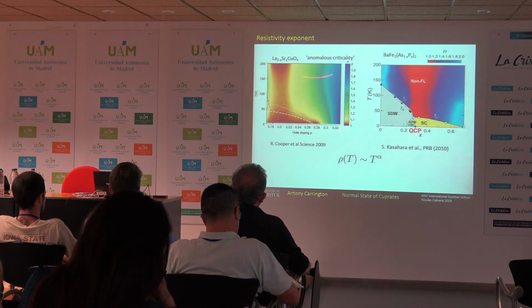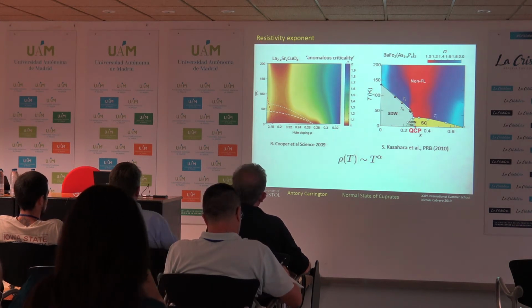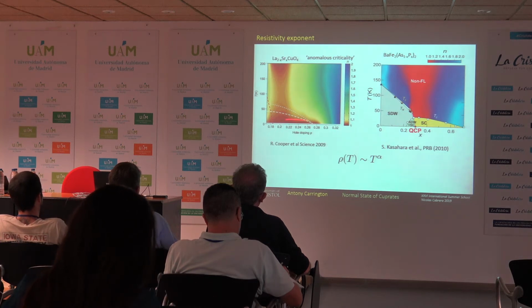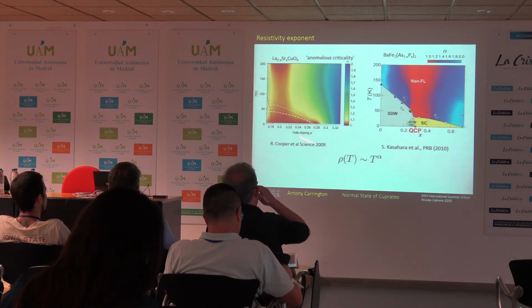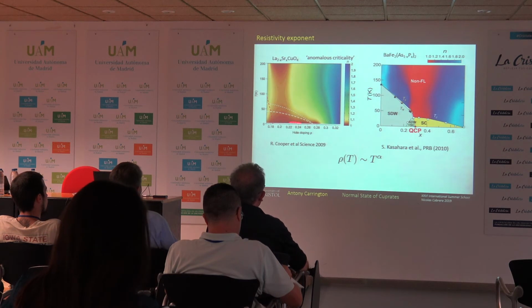And then secondly, the nice thing about this is that you can easily suppress superconductivity with a high magnetic field. And indeed, what you find is that at very high overdoping, you get this T-squared behaviour, and then linear behaviour at optimal doping, but interestingly, the linear behaviour seems to actually extend to low temperature. So it has this kind of shape, it looks like a foot, rather than a fan.